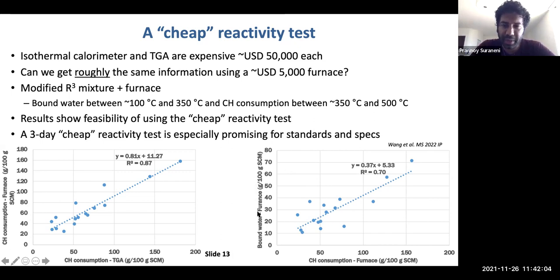Scrivener and others have shown that bound water and the heat release actually correlate pretty nicely. So the bound water can be used as a proxy for the heat release. And if you plot bound water versus calcium hydroxide consumption, this can be a way to rapidly classify materials. You can use it in 3 days, and you can use a cheap furnace to actually make this happen. So a 3-day cheap reactivity test is especially promising for standards and specifications. We are in the process of writing this paper, but the results have been quite nice.